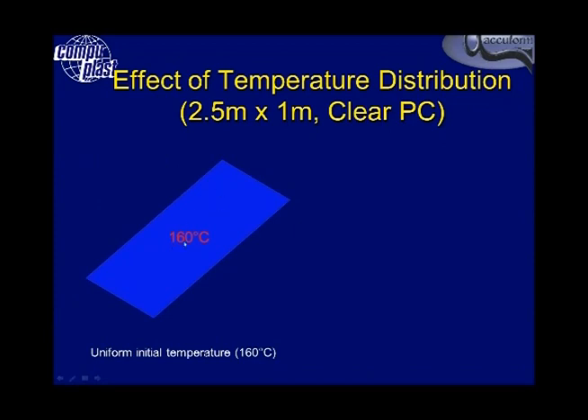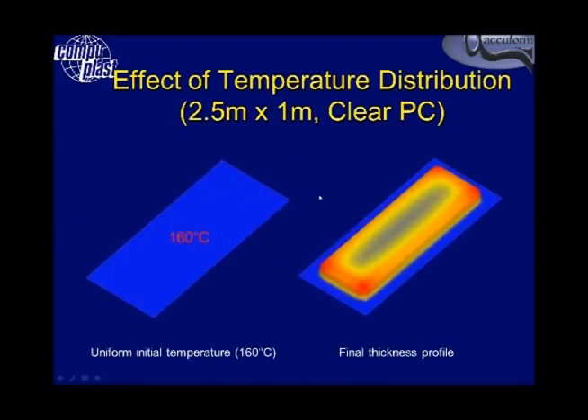Another example involves a large sheet of clear PC formed to make a large sign, such as those you'd see on highways or at service stations. You can see the thickness variation, particularly in the corners where the material gets quite thin and can be fragile and break. Each sheet can cost up to a thousand dollars, so performing experiments to achieve more even thickness distribution is costly. Plug assist is not acceptable for a clear product because the plug can leave marks on the surface.